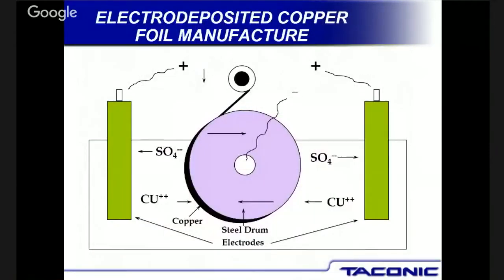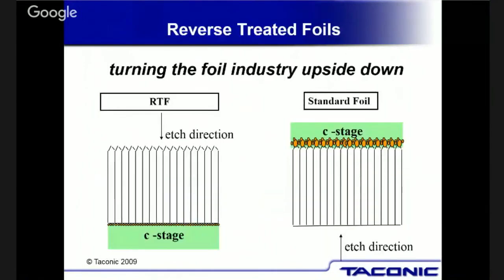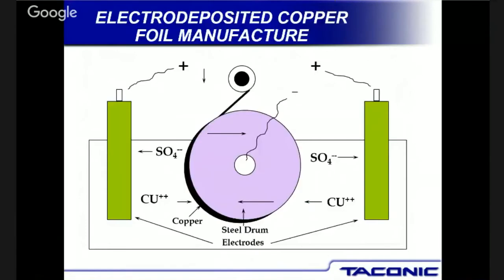But that is an issue. And so, in fact, what we're doing a lot is supplying what I call reverse treated copper. When I was showing that picture, I'll switch back here to the drum. There's two sides of the drum, and everybody relies on the tooth of the copper to make it stick. What we've been doing for a number of years is we're actually laminating the smooth side of the copper to our material. And so we're putting the tooth up. It's a little tricky because it does affect bond strength, but we've worked through that, and I think our expertise is we figured out how to get really smooth copper to stick to our materials.